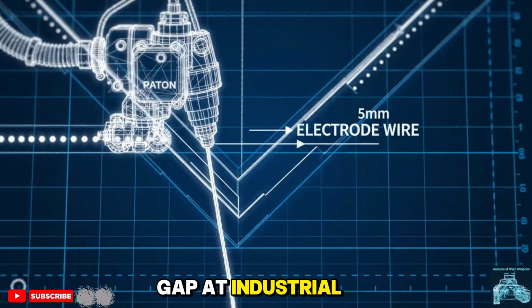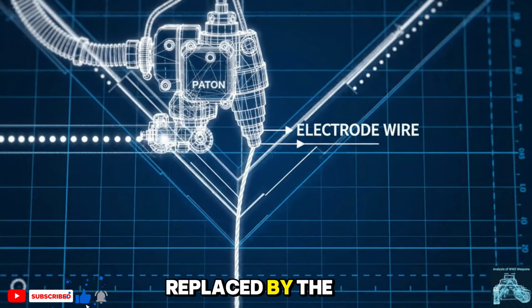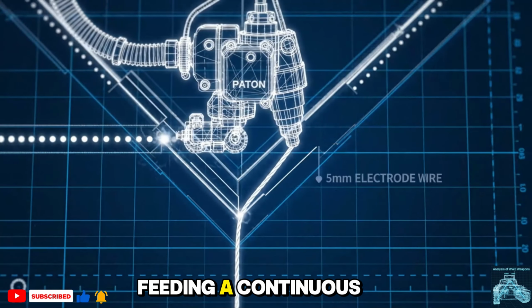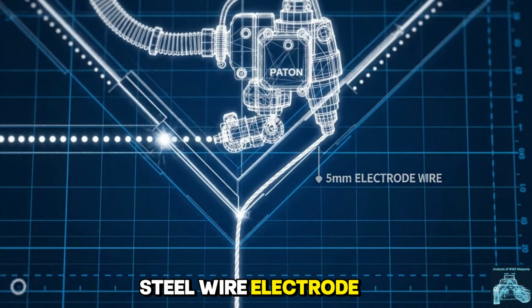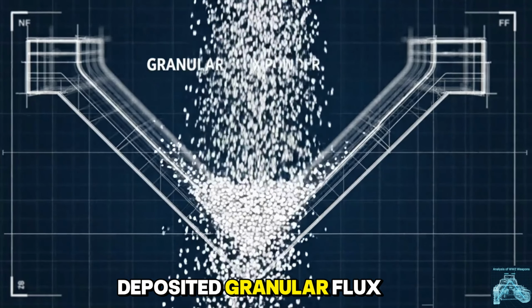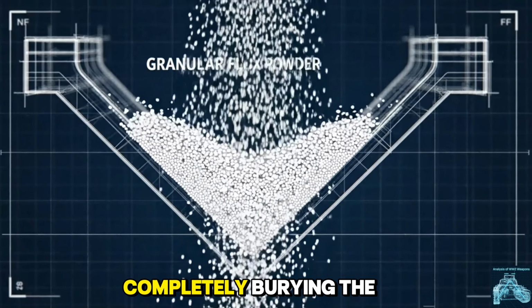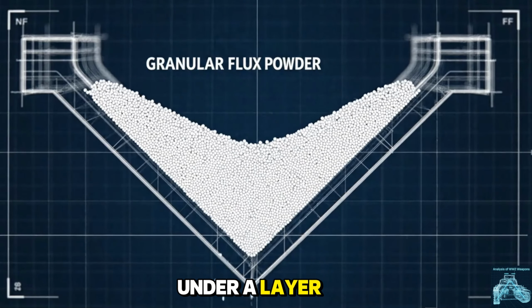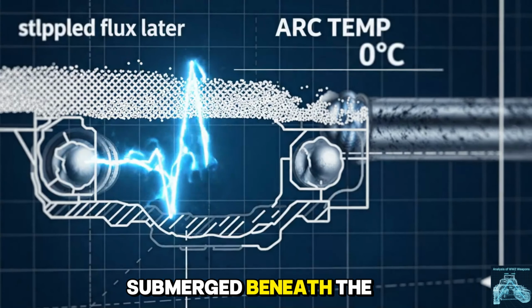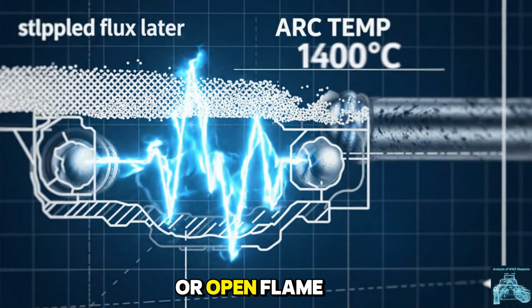To fill this gap at industrial speed, manual welding was replaced by the Paton automatic welding head, feeding a continuous 5mm thick steel wire electrode. Before ignition, a copper funnel deposited granular flux powder over the joint, completely burying the 5mm gap under a layer of protective silicate mineral stones. Submerged beneath the powder, a 1,000-ampere electric arc ignited. Without blinding glare or open flame, it generated a localized zone of 1,500-degree heat.